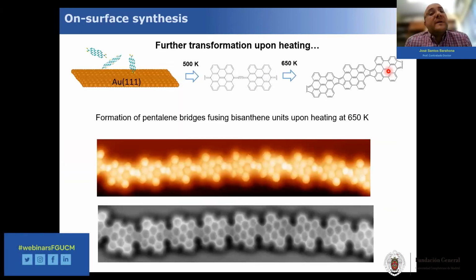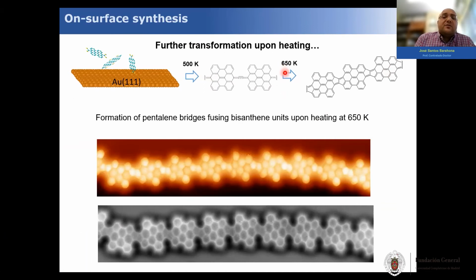Well, a further transformation that can be observed in these polymers is that when you overheat them at 650 kelvins, we observe another reaction, which is also new. Here you can see that the cumulene linker between the bisanthenes transforms into a pentalene linker. Again, you can see how neat the images are. You can discern perfectly every atom, every single ring of the system.